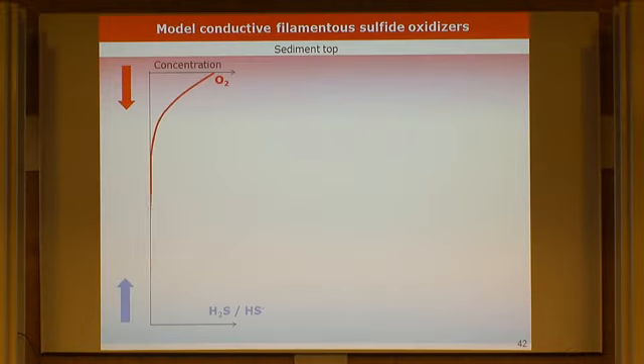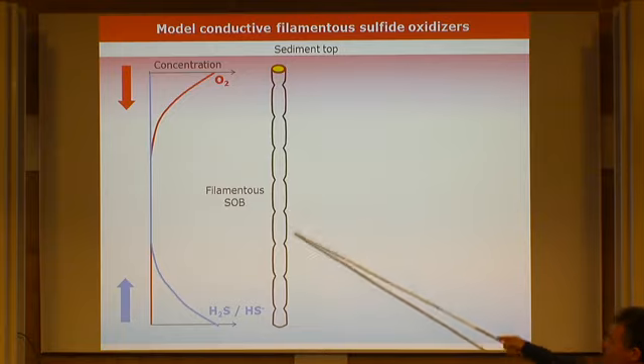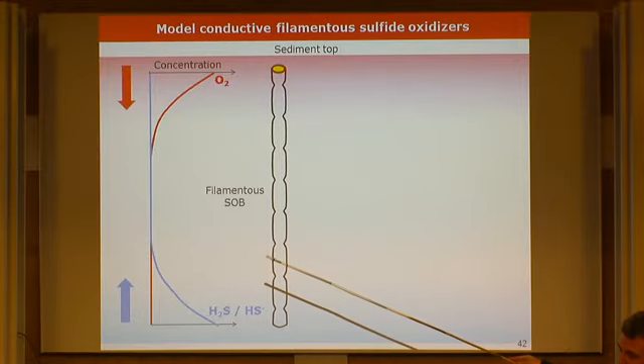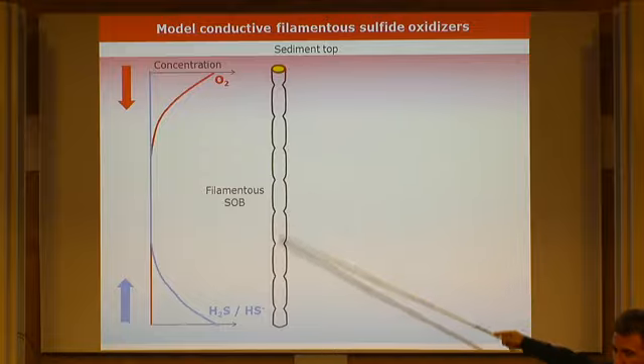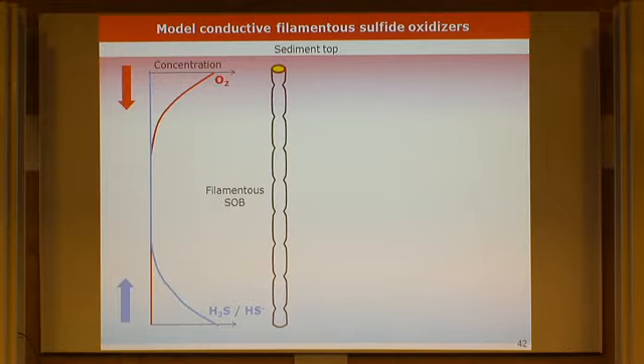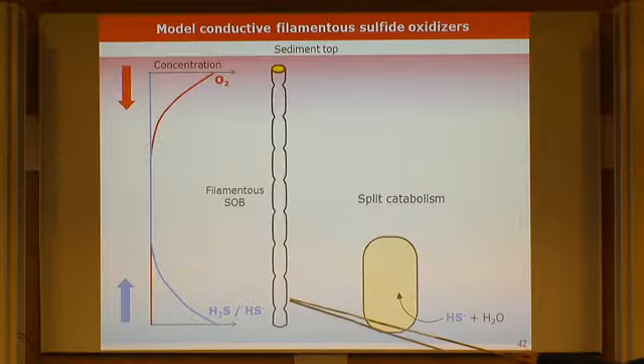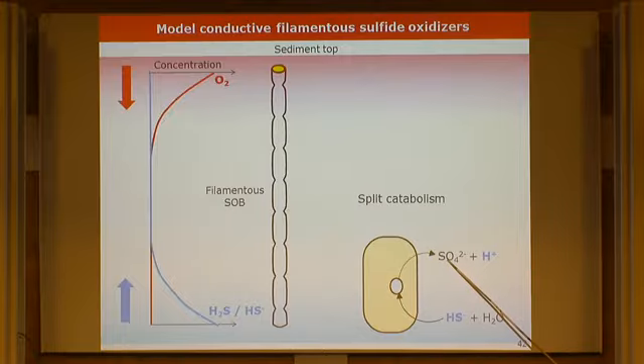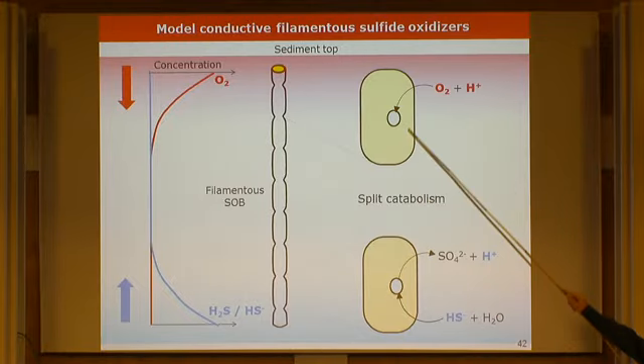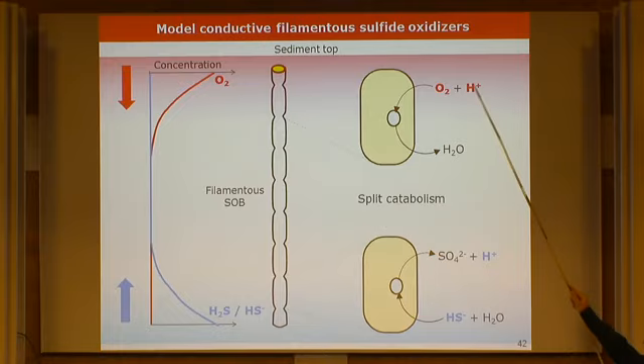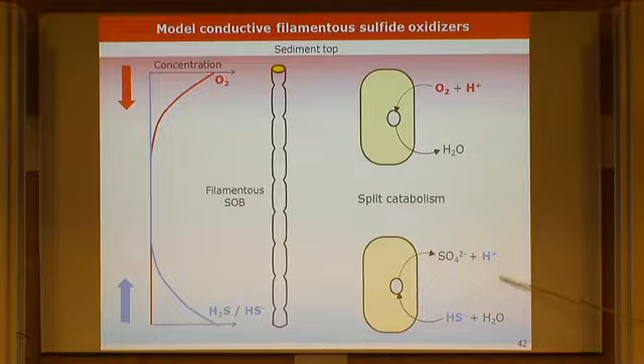And well, we try to make a model now so that we can explain these profiles and what is the effect of conductivity now and how long can these filaments actually grow until they are limited, either by substrates or by conductivity or other things. So we have the filament, substrate concentrations, and we try to put a split catabolism now. So half of the reaction is done by cells deep in the sediment, the sulfide oxidation to sulfate, and the cells here at the top perform oxygen reduction. So you can see here from the reaction, they consume protons here, so this should become alkaline, and they produce protons here, this should become acidic, this part.